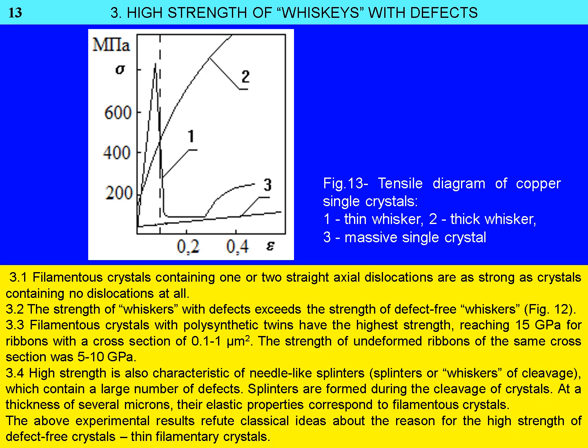Figure 13, Slide 13, shows the plastic deformation curve of a thick copper whisker, curve 2, which reached a high strength, 1200 MPa, exceeding that of a thin, undeformed whisker, curve 1. Additional data presented on Slide 13 confirm that deformed whiskers and whisker-like structures with defects can also exhibit very high strength. This contradicts the classical view that the high strength of whiskers is solely due to their perfect structure.